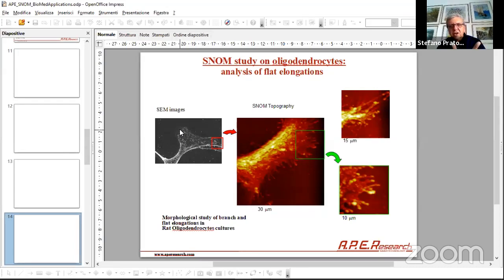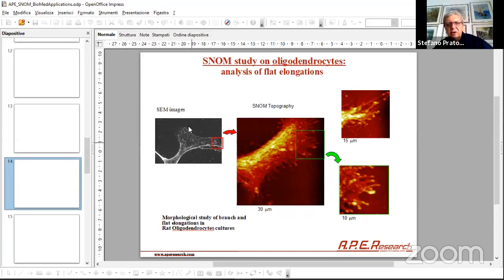So how much is this amount of gold that you put on top? A lot of biologists do not think about that. But what you put on top is between 10 and 20 nanometers of gold. So it's like putting a carpet of 10, 20 nanometers on top of your cell. That's why those small structures are not visible anymore, because they are smaller than the gold or the carbon or the coating that you put on top of your cell. I don't know if it was clear enough. So this is what you get with SEM: no details on the outer part, and with AFM you have a lot of details on the outer part.